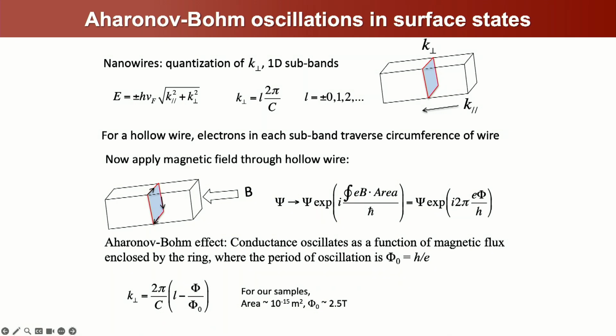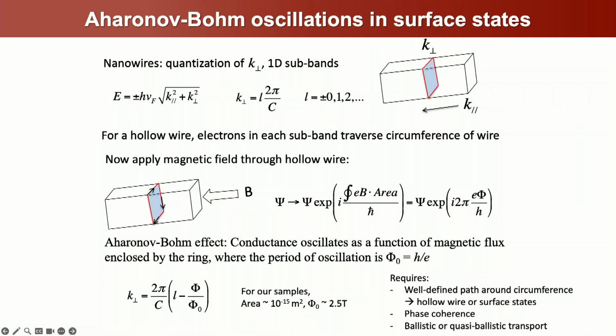Okay? Now, there are some conditions here. You have to have something small enough that you get quantization. So in our case, we have a very small area. It's only, like I said, a 15 nanometer thick wire, 100 by 150 nanometers. We have a small area. We expect to see a flux period of oscillation around 2.5 Tesla, which is accessible. You also have to have a well-defined path around the circumference. So we're applying a flux through a 3D material, which actually has stuff in the middle, which is the business of the solenoid.